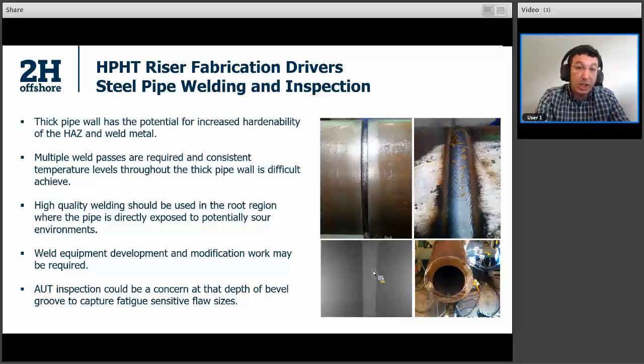Of course, we are talking about the sour region, and we need high quality welding in the root region where the pipe is directly exposed to potentially sour environments. High quality welding means difficult fabrication and more fabrication time. In addition, for thick wall pipe with high quality welding, welding equipment needs to be developed or modified, and that will bring other challenges to the system. If you are changing or redesigning your weld equipment, you need to train your welders again. That's another challenge. And of course, for this thick wall pipe, after welding, AUT inspection is challenging, especially to detect fatigue sensitive flaw sizes in the root region. So definitely fabrication and inspection is difficult.